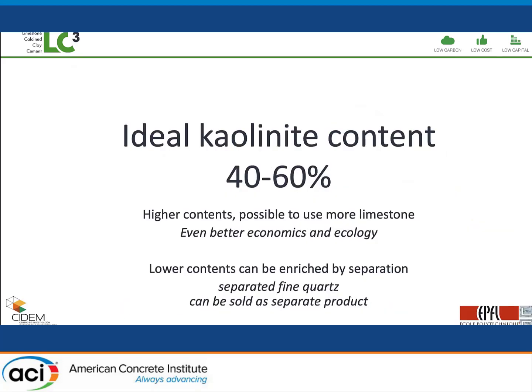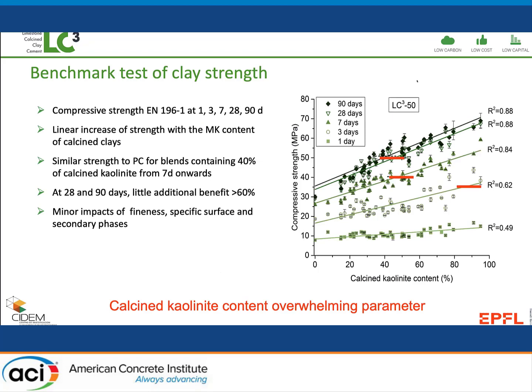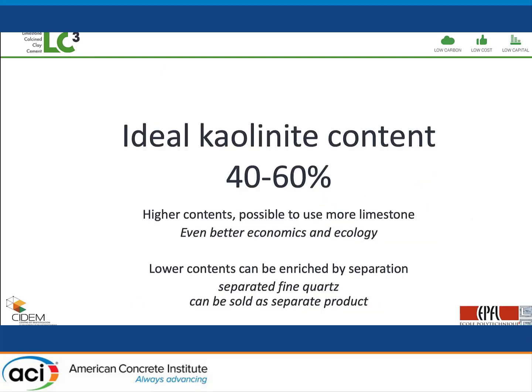So just summarizing that, we kind of say the ideal kaolinite content is 40 to 60%. If you have higher contents, then the benefit is you could just put in more limestone, because if we go back to this graph here, you see that there's really very little extra gain going above about 60%. So you may as well put in more limestone. You get even more reduction in CO2, and it's even cheaper, and you can improve still further your rheology.